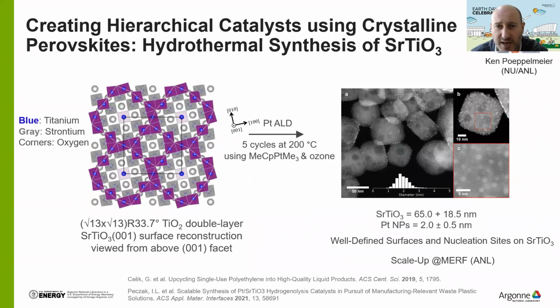First things first, when we start to think about this problem, all this carbon-carbon bond cleavage using hydrogen requires high temperature. That means we need to stabilize in some way the platinum nanoparticles on the surface. It's a heterogeneous catalyst. For example, under hydrogen at high temperature, nanoparticles tend to sinter and form bigger nanoparticles. And then when they start to sinter, they lose their activity.